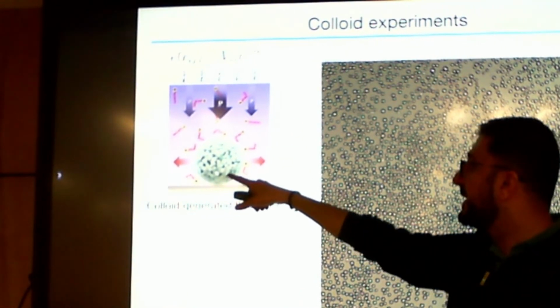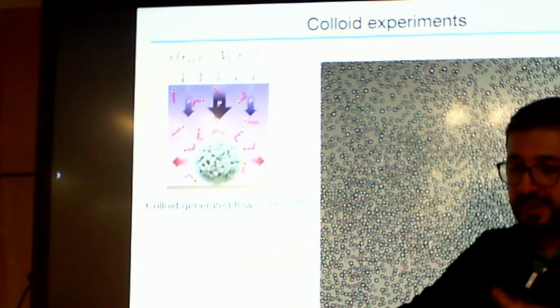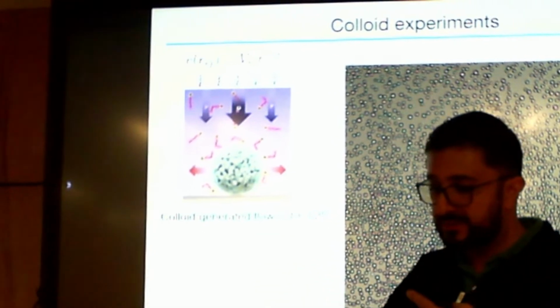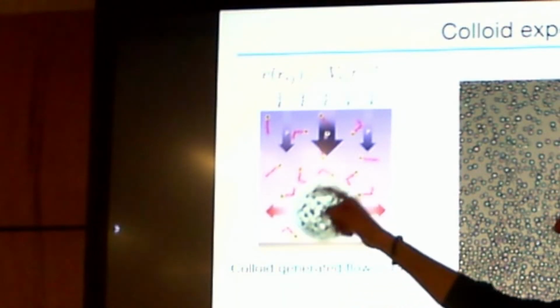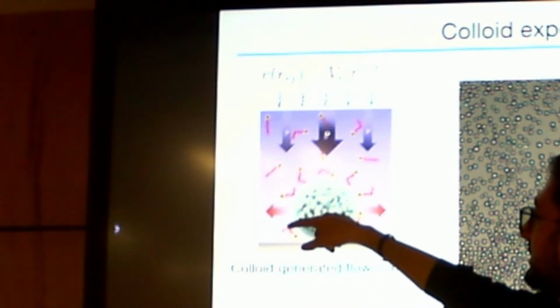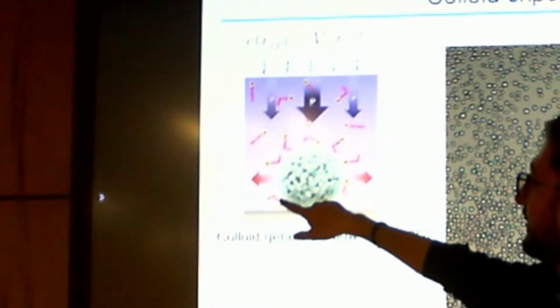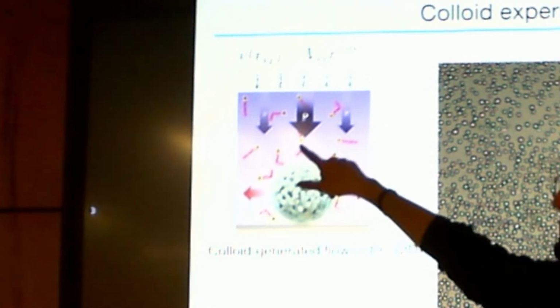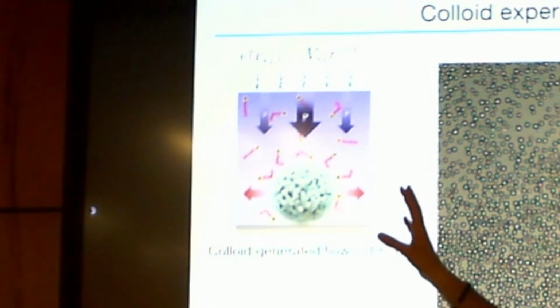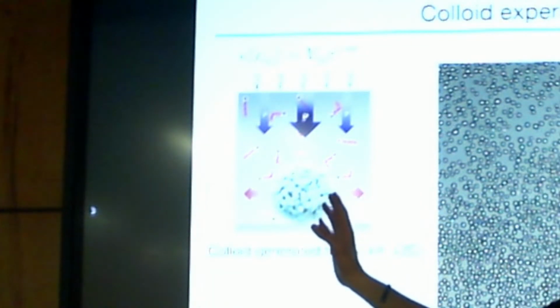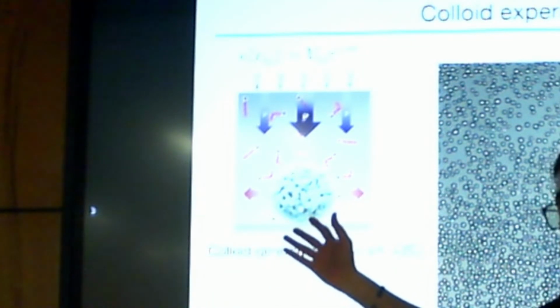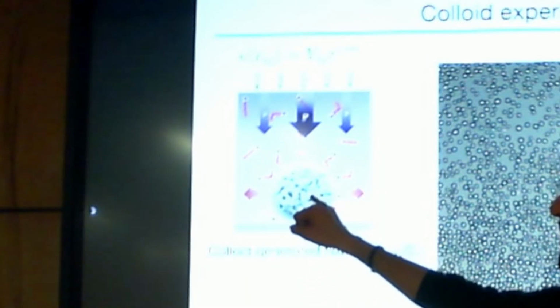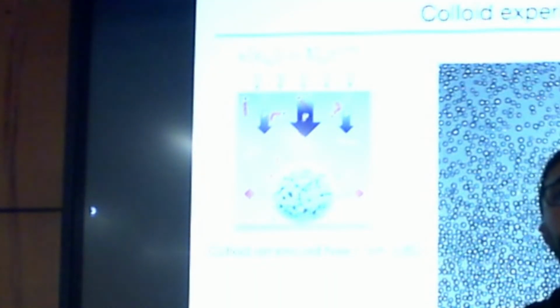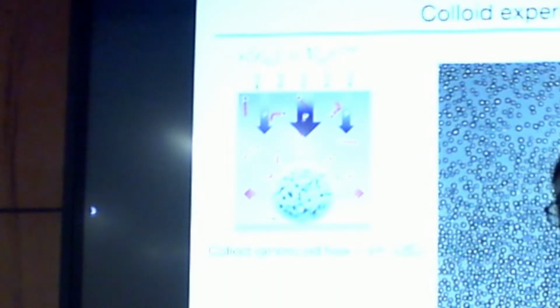And then there's a chemical reaction going on. It is like a constant in and out. So this creates a density field which is higher around the particle, of these cis and trans molecules, than outside. So there's a density gradient which creates diffusophoresis, which means basically these particles push out the flow in order to homogenize the density of these molecules.